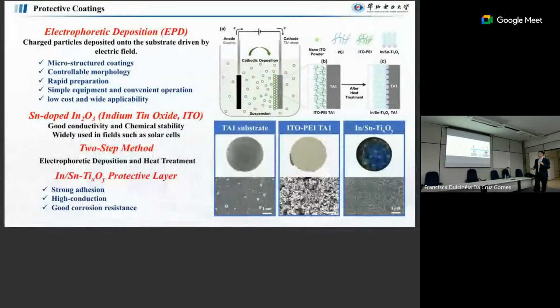Yeah. And another one we developed is electrophoretic deposition, the EPD technology. This is not a new technology. People have used it for a long time. Yeah. But the problem is, normally the coating produced by this technique is not stable on the surface. Then we tried to optimize this technique. Then we get very, very stable coating layers on the surface. And here we use ITO. Normally, indium is also an expensive metal. But the good thing here is we take this ITO from PV panels. Yeah, it's waste for them, and we reuse the waste in the system.